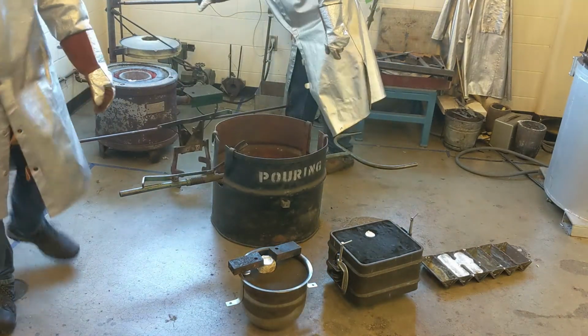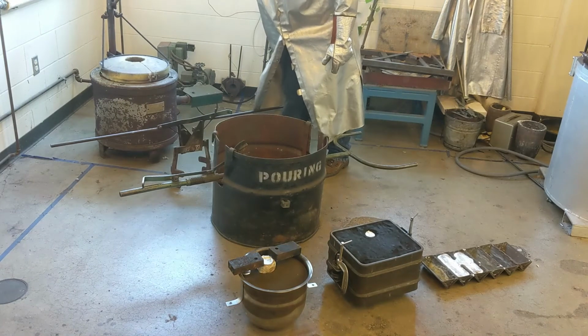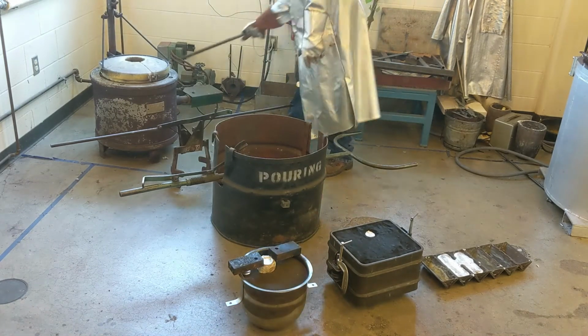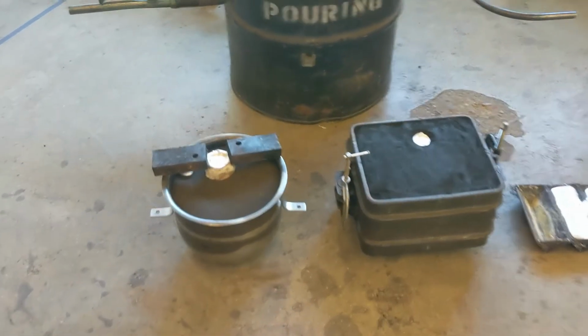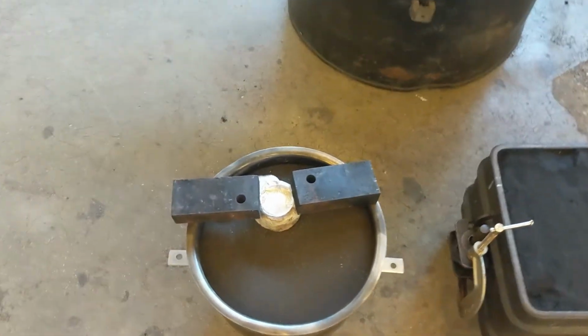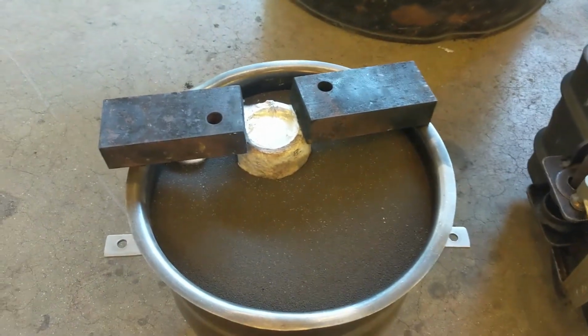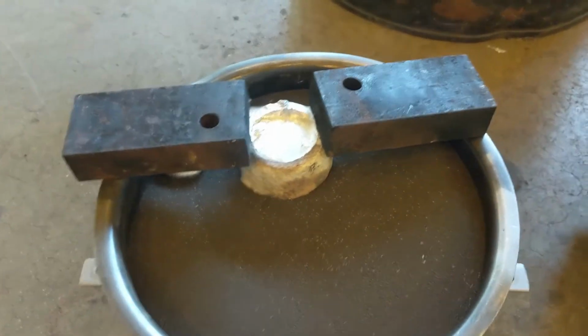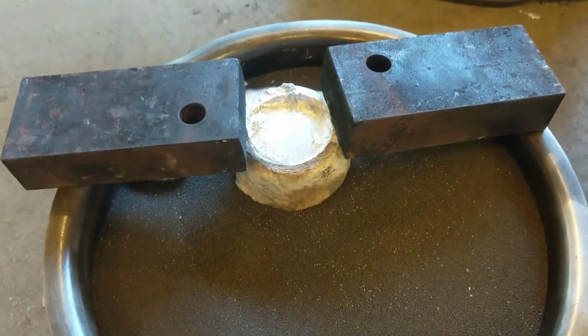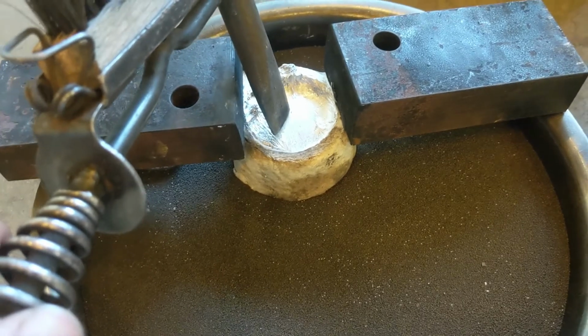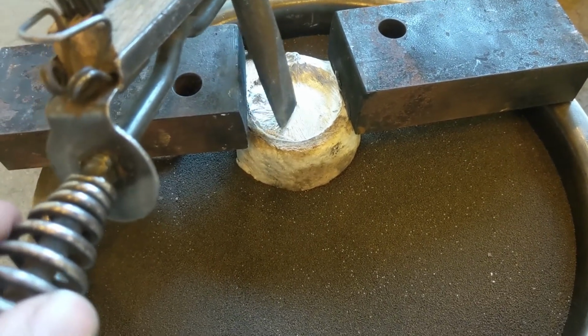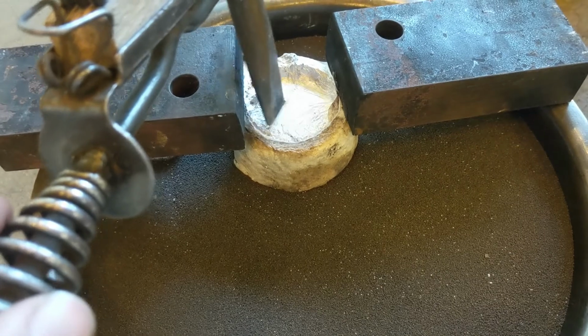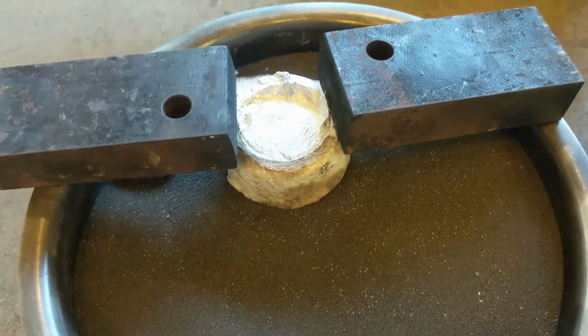Very good work. Okay, we've just poured these castings about 20 seconds ago. And so this is when we want to notice the effectiveness of the insulating sleeve. So here's the lost foam casting, and you can see that the oxide layer is formed on the top of the aluminum, but that insulating sleeve is keeping that completely liquid.